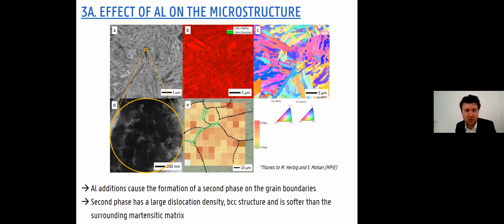When taking a closer look, and I have to thank here the people from the Max Planck Institute in Düsseldorf, Michael Herbig and Saurabh Mohan, for these measurements, we could see in figure A needle-shaped dark regions at the prior austenitic grain boundary. The darkness indicates that the regions contain a higher dislocation density compared to the martensitic matrix. In B, we can see the dislocation structure based on ECCI data. With the EBSD, you can clearly see that no gamma was present. So this is not austenitic, this is purely a ferritic film that was formed. So it's not delamination, it's not open space, it's a phase that is present at the prior austenitic grain boundaries. Aluminium additions as a ferrite stabilizer cause the formation of a second phase on the grain boundaries. The second phase has large dislocation density, a BCC structure, and is softer than the surrounding martensitic matrix.